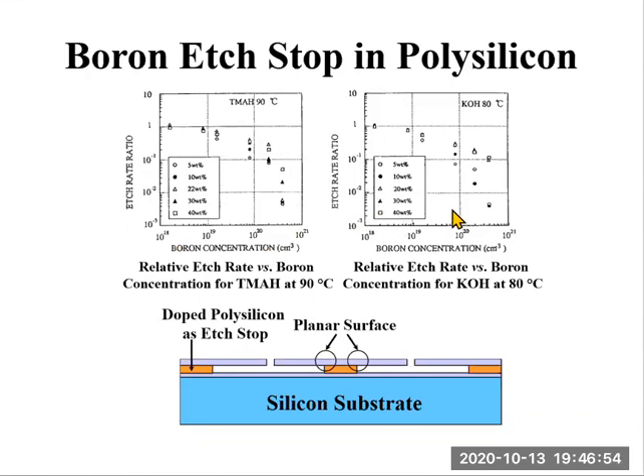Similarly, the right figure represents the relative etch rate versus the boron concentration for KOH at 80 degrees C. Again, we observe that the etching rate can be reduced by 10 to 100 times due to the boron etch stop. As shown in the bottom figure, the heavily doped polysilicon can function as an etch stop. It can be used to control the sacrificial etching. So this is actually a useful feature in sacrificial etching.